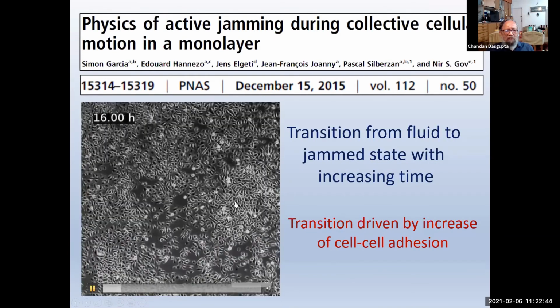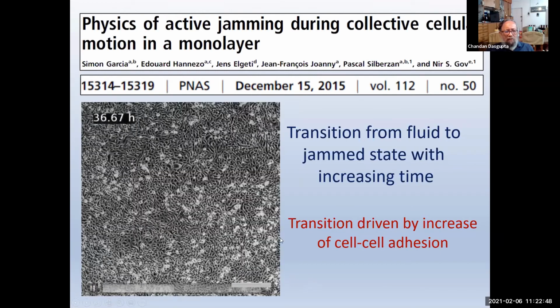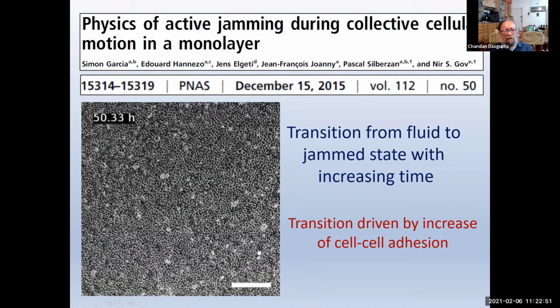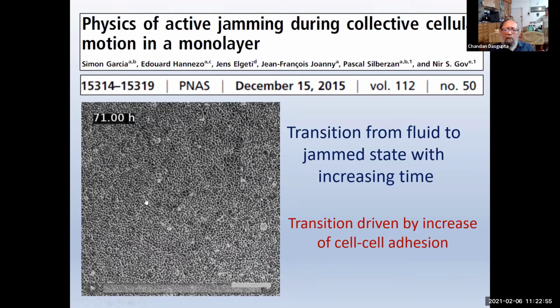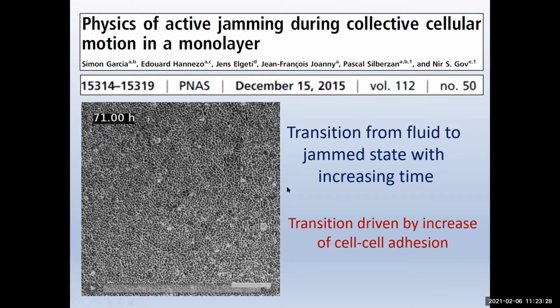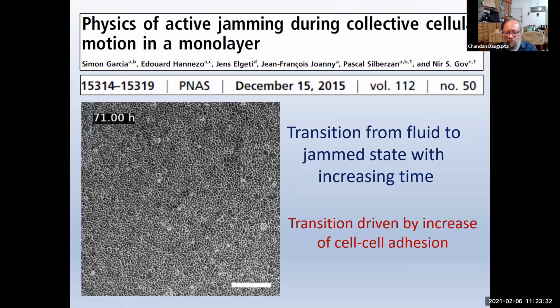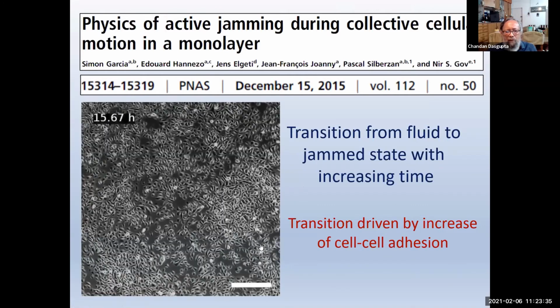So this is basically the transition from a liquid to a glass, in the sense that one is starting with the usual liquid, and then as a function of time, one is getting into a state in which the cells are basically stuck. And the biophysics tells us that as time increases, cell adhesion is increasing, and that is driving a transition from the initial liquid state to a final glassy state, as some parameter, here the cell adhesion, is varied. So these are the kind of phenomena that we'll be interested in: you have a liquid and then some parameter is changed and the dynamics becomes very, very slow, and it continues to slow down as this parameter is changed further, and eventually it ends in an arrested state, which you can call a glassy state or a jammed state. So these are examples taken from biology.